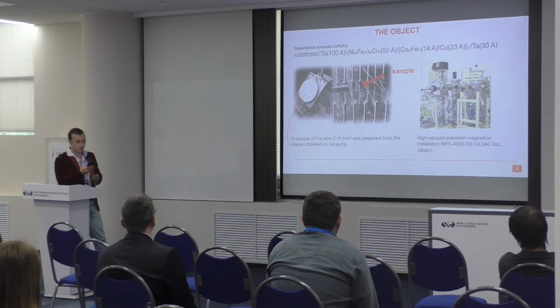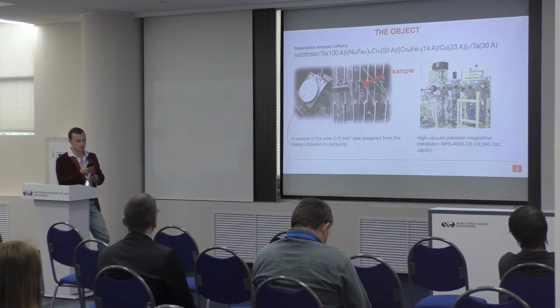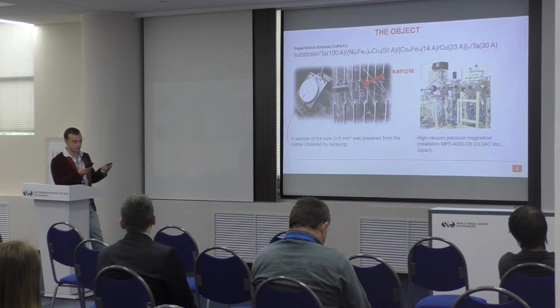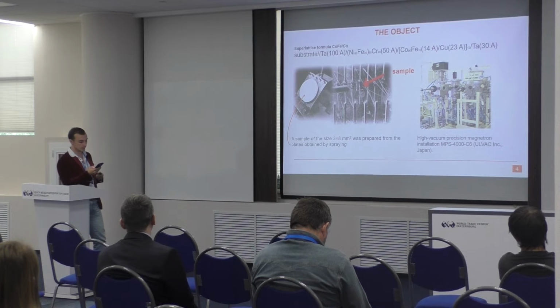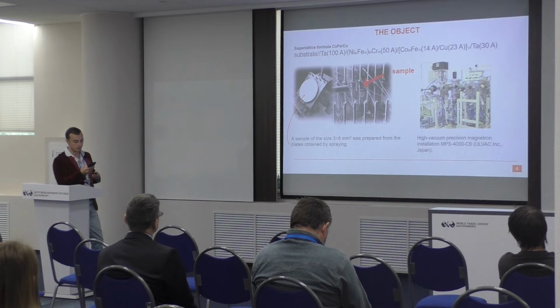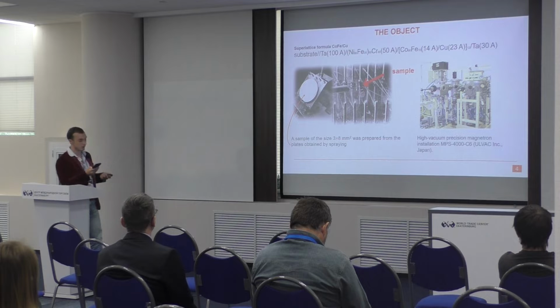on the screen. The formula of the resulting superlattices is indicated on the slide, where the substrate is, as I said before, either monocrystalline sapphire glass or monocrystalline silicon, in which the cobalt iron alloy is used together with the copper layers. Basically, cobalt iron copper superlattices are polycrystals with an FCC structure and a sharp axial texture in the 111 direction, with the texture axis perpendicular to the substrate plane.